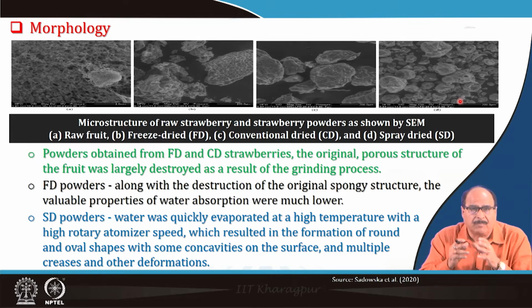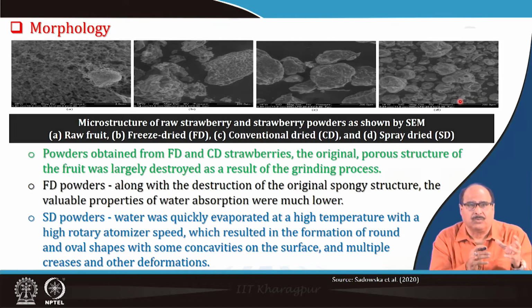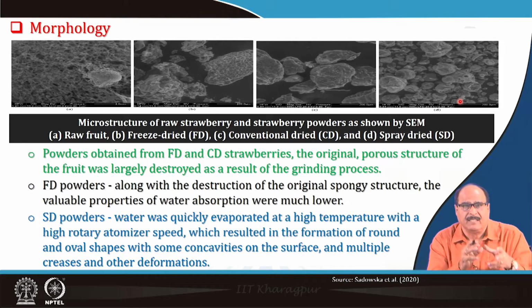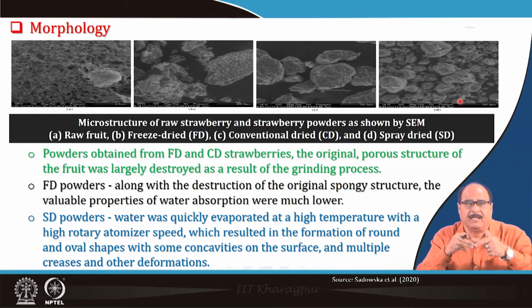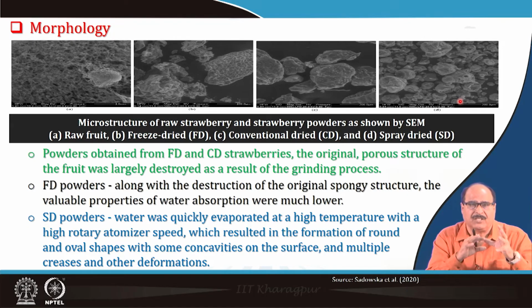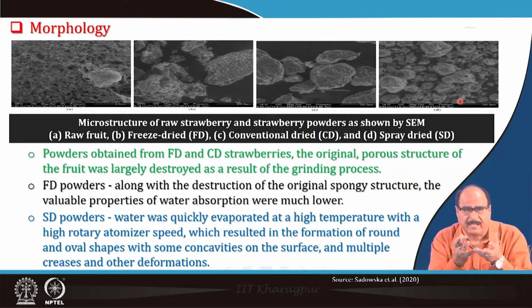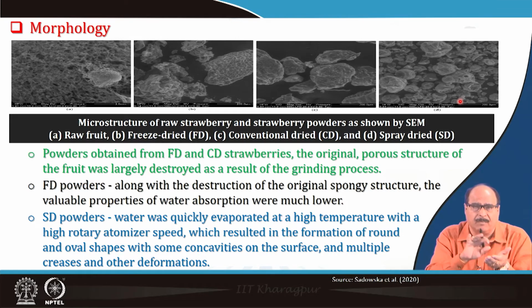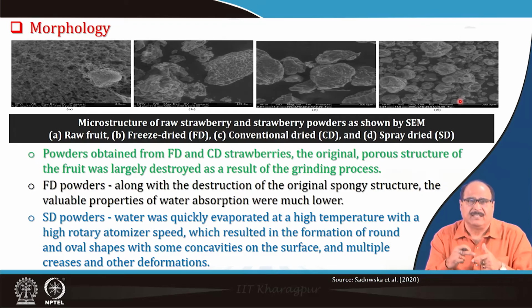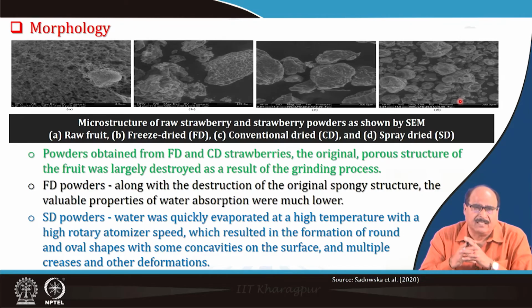The powders obtained from freeze dried, spray dried, and conventionally dried methods, their original porous structure of the fruit was largely destroyed. This is mainly as a result of the grinding process, because after freeze drying or conventional drying it is in the form of flake or sheet, and during grinding the original structure is destroyed.